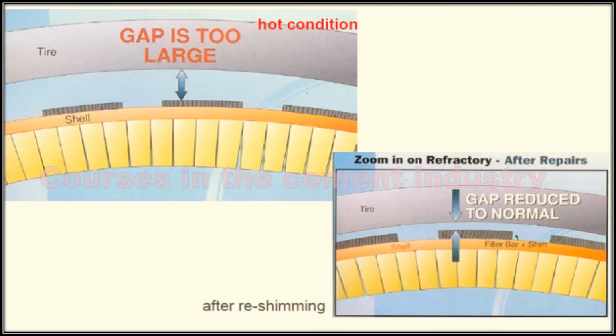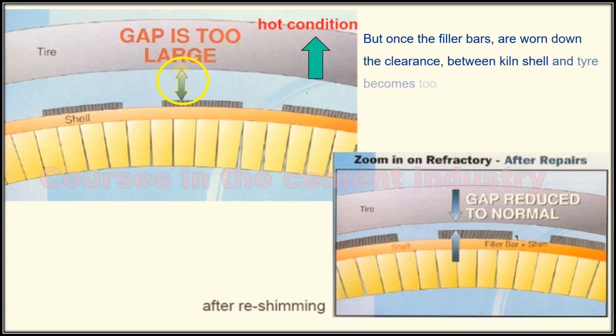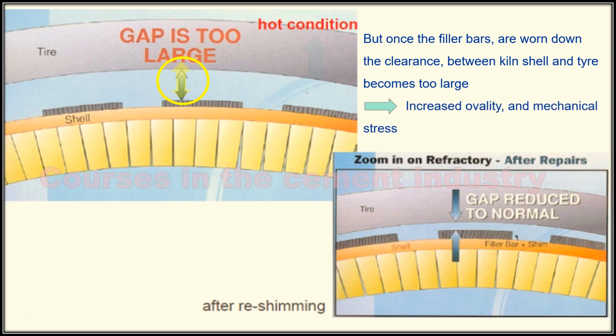In this photo we watch the gap is too large in hot condition. Once the filler bars are worn down, the clearance between kiln shell and tire becomes too large, which causes increased ovality and mechanical stress. This photo is after reshimming. The gap is reduced to normal.